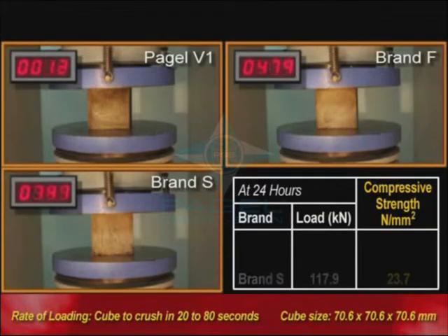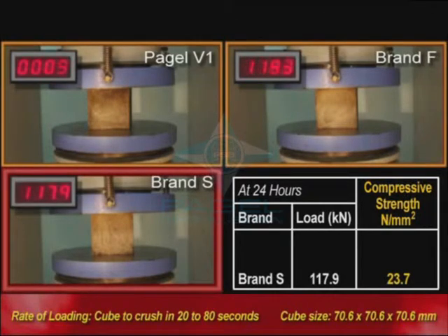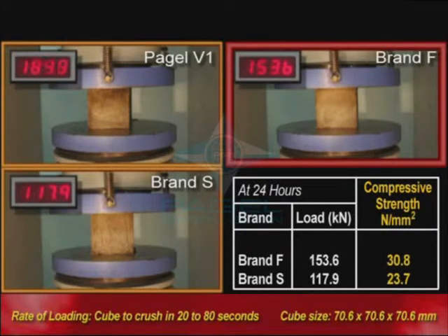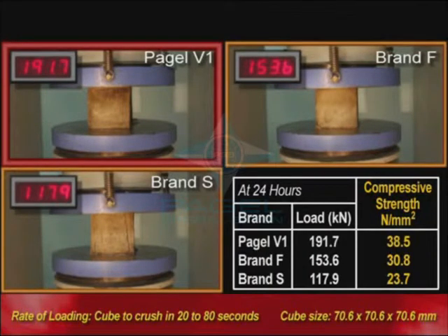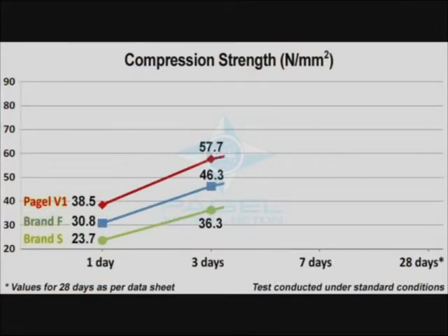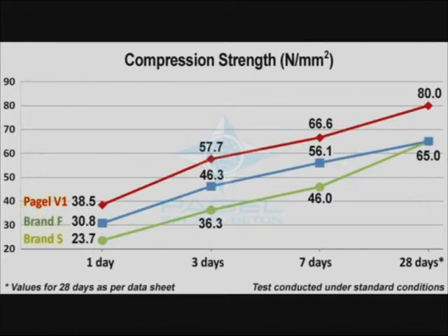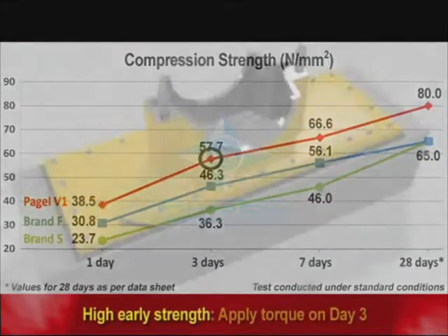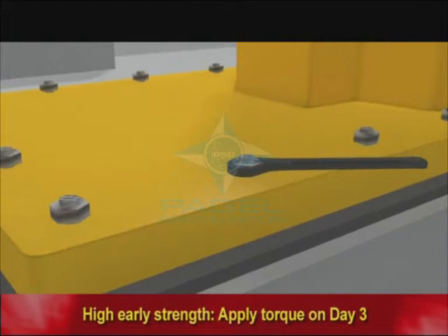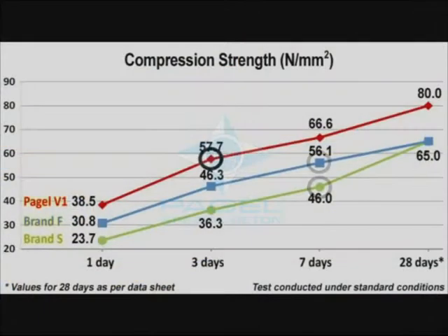As we see, the grout of Brand S cracks at 23.7 Newton per square millimeter. Brand F has a compressive strength of 30.8 Newton per square millimeter. However, Pagel V1 grout can withstand 38.5 Newton per square millimeter. The same test at 3 days, 7 days and 28 days after casting shows Pagel V1 develops high early strength, allowing you to apply torque on the foundation bolts even by day 3. With other grouts, you would have to wait at least till day 7.